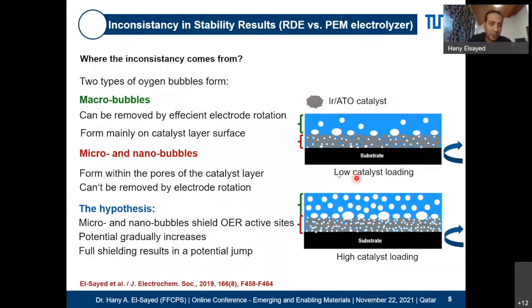We do have a hypothesis here, and our hypothesis is that we always have oxygen evolution, and the oxygen evolution produces not only big bubbles, but also micro bubbles that can form within the catalyst layer. When you do an RDE experiment, you are always keen to remove the bubbles that we can see, and the macro bubbles can be removed by rotation. That's not a big issue. We believe that the micro bubbles inside the electrocatalyst layer, in its porosity, cannot even be stirred out, and they have no motivation to get out of the layer because outside is already oxygen saturated. So we really think that the accumulation of these microscopic oxygen bubbles is responsible for this phenomenon.